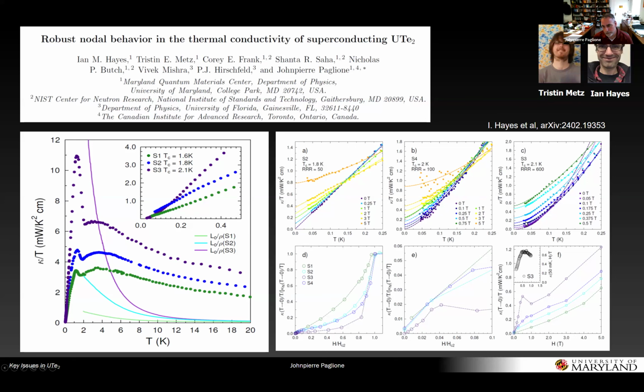And what we're very proud of is that in this highest TC sample, we were able to get the experiment down to 30 millikelvin, and to keep that as a function of magnetic field. You can see here that the extrapolations are not very trustworthy from the lowest temperature data. If you look at the data below 100 millikelvin, there is quite a bit of curvature. So you really have to do this experiment to the lowest temperatures to understand what's happening.